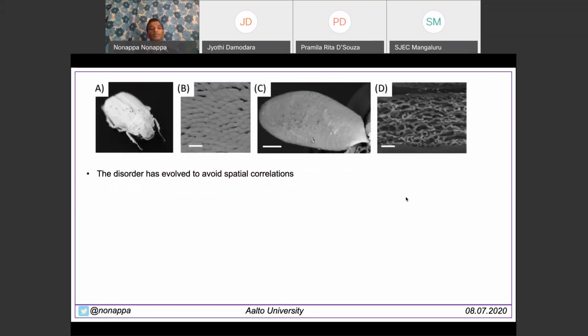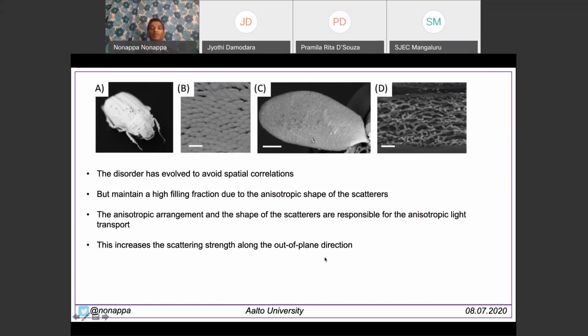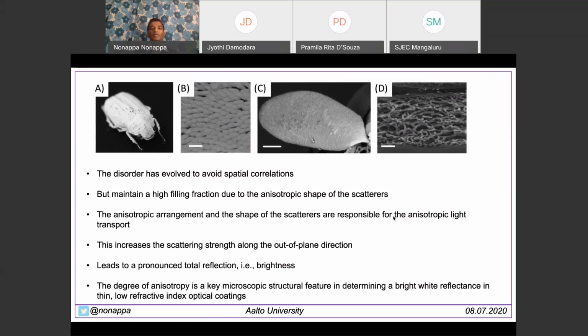And a little bit more on how disorder helps: it helps us to avoid any spatial correlation. It fills the space, but there is a lot of void in between them. And you can create this kind of structure simply by following this principle. This is why many insects are able to do this. And we can actually change, for example, if you have a highly transparent material where complete light transfers, you can change the order in it, and it can turn bright. And such examples are known in literature.